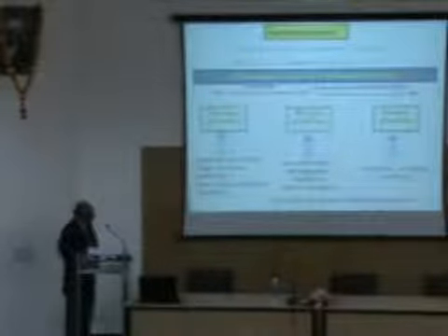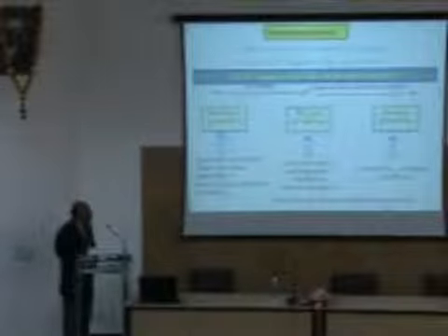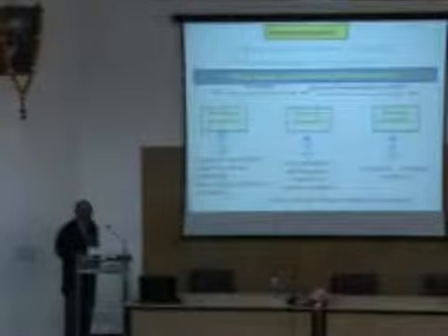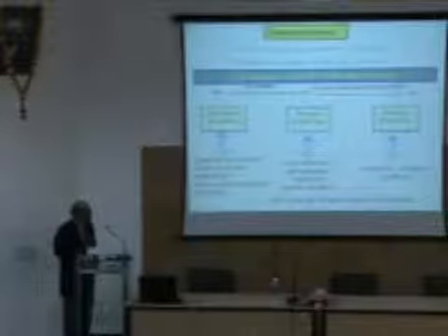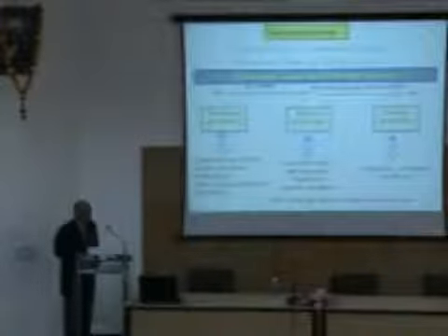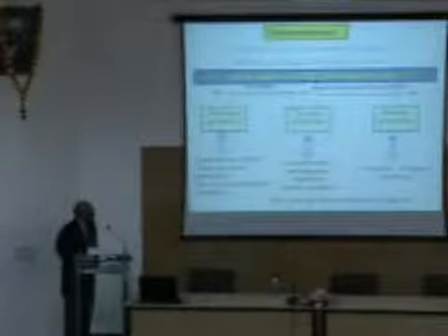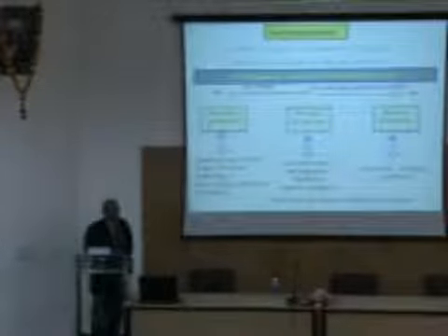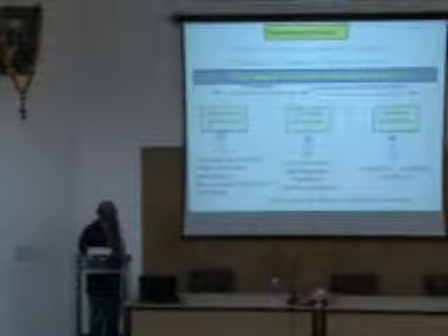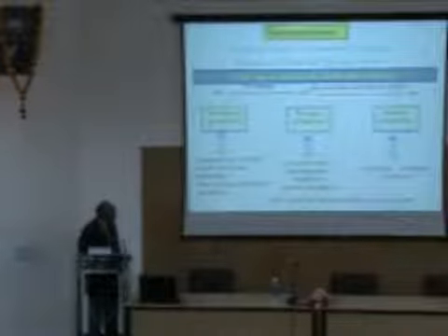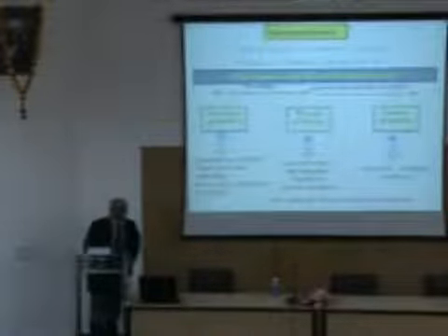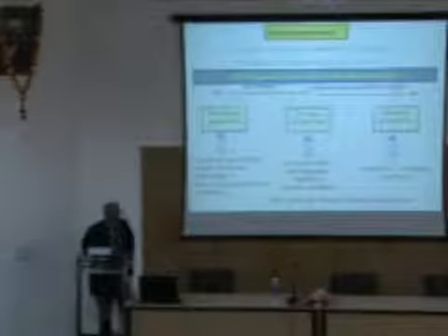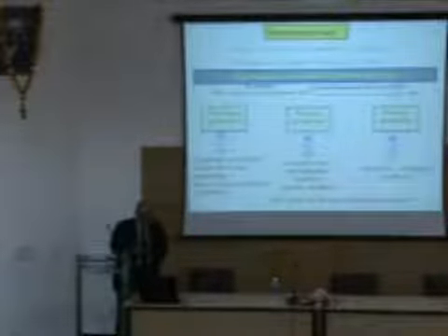If you are a material scientist, you know you have changes in the microstructure, the melting point reduces, the ductility changes, the hardness changes, and from the activity point of view, your structure can change, your catalytic properties certainly get enhanced. The surfaces and interfaces become important because the size of the particles is so small that there are hardly any particles in the bulk.